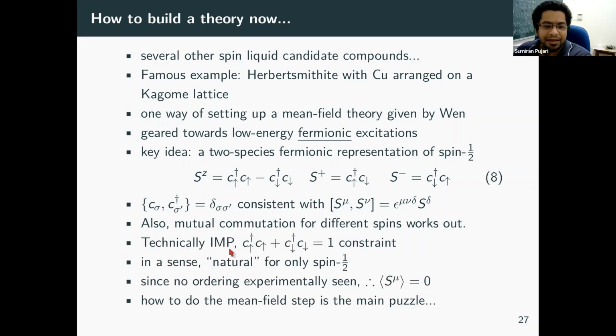And there is an additional technically important detail, because if you have two species, each fermion can be occupied or unoccupied. So therefore the Hilbert space is dimension 4, whereas the spin Hilbert space is dimension 2. So you take care of that with this additional constraint. And this fermionic mapping is only natural for spin half in some sense. So whenever you believe that the low energy excitations of your magnet or spin liquid are fermionic in nature, you would use something like this. Since no ordering has been seen in this material, we again will suppose a mean field of the spins themselves will be zero. Whereas in the Ising or the spin wave case, we had assumed this would be non-zero.